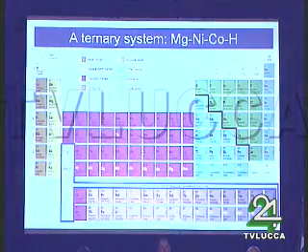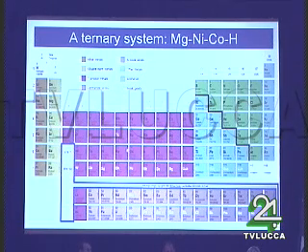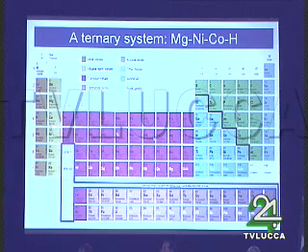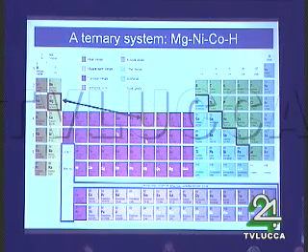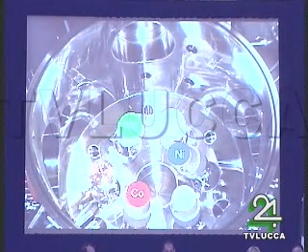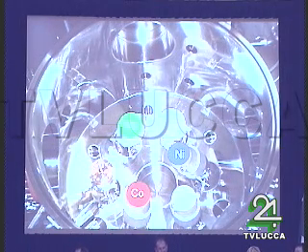Okay, now let's go to something else. I mean, it's not very original to talk about magnesium transition metals, but it's just to illustrate the technique. Of course, making a gradient from magnesium rich to nickel rich is educationally correct, but for combinatorial purposes, you would like to be more complicated. So I give you this here as an example of a ternary system, and it is magnesium, nickel, and cobalt. And the trick here is now you use three sputtering guns. In fact, we have 6, and we can do more complicated games. But let's say these 3 here.